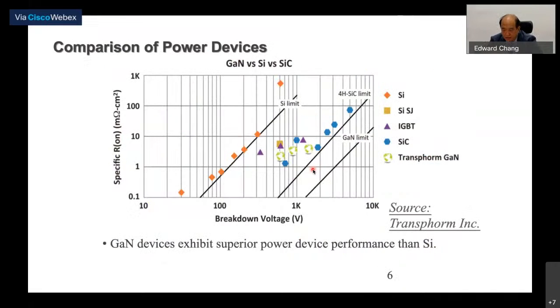So this is the comparison of the material as a power device. As we know, the structure gives a very high current because of the electron density, and the band gap also gives you a high electric field. So overall, this material gives you an advantage to be used for power applications. And compared to silicon IGBT and silicon carbide, you can see that it gives you a much higher breakdown voltage with low specific on-resistance because of the high current, high carrier concentration within the material.